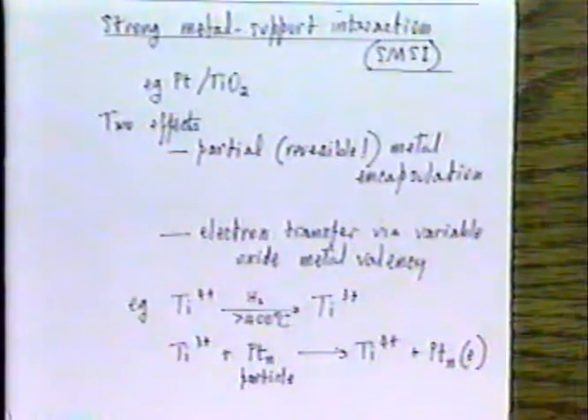When you have platinum supported on titania, when the platinum is reduced in hydrogen at a sufficiently high temperature, the platinum becomes at least partially inactive towards hydrogen chemisorption. And that arises, it's now fairly clear, from the operation of two effects operating simultaneously. One is that in the high temperature reduction of platinum titania, the titania is able to migrate over the surface of the platinum to some extent, and there is an encapsulation effect. That is, the titania which migrates, and you can regard it, if you like, as adsorbed TiO2 on the surface of the platinum. The titania on the surface simply acts as a blocking agent and prevents hydrogen chemisorption.